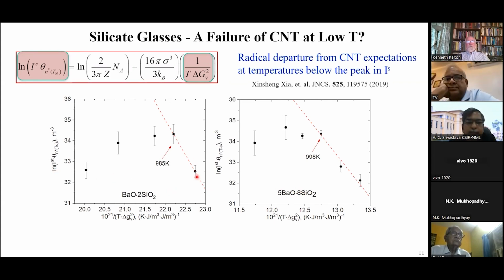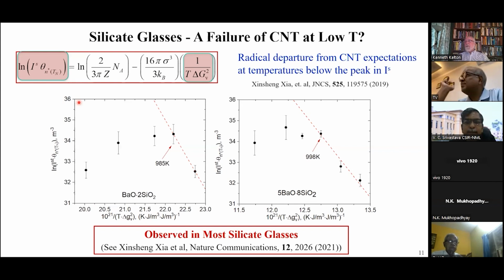These are the measured values that you have for the steady state rate and the induction time from those two-step annealing treatments. In both cases, you find that at high temperatures, you can get a reasonably straight line. But as you go to low temperatures, which is going toward the left, it departs radically from straight line behavior. Since this is a log, we're talking of orders of magnitude departure from a straight line. These are two examples. However, this has been observed in multitudes of silicate glasses.